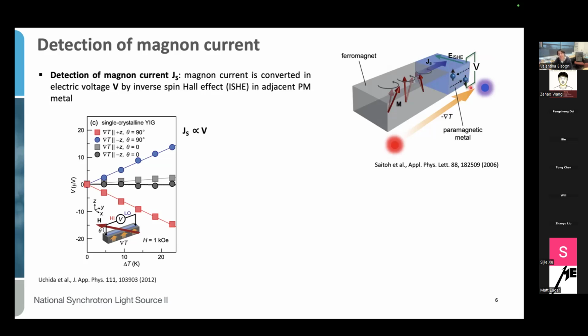By measuring the voltage as a function of, for example, temperature gradient, as I represented here in case of a spin Seebeck generated current, we can see that the voltage measured across the platinum increases as we increase the temperature gradient, which means that actually we are increasing the amount of spin current created in our material, and it is found a very linear proportionality between the spin current and the measured voltage by inverse spin Hall effect.